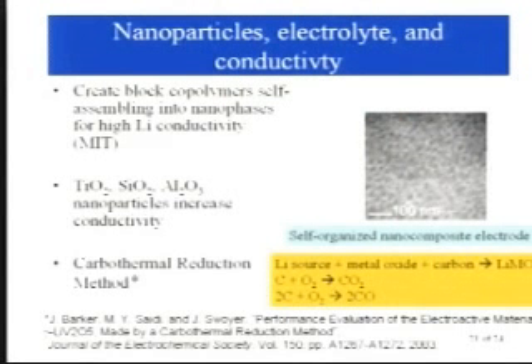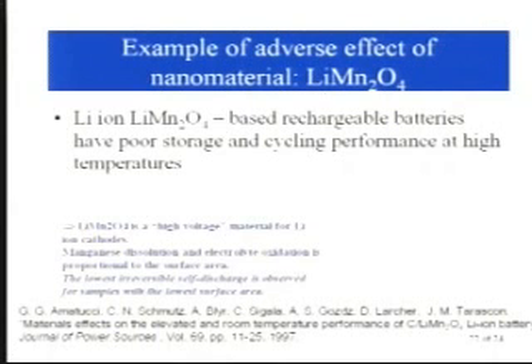And I mentioned the carbothermal reduction method a few times, and essentially what it is is use of grinding carbon in with a precursor, and there's a reaction of oxidation of the carbon. This is a very old metallurgical process, and this reduces the precursor and gives you a final product. And so there's a lot of interest in that. But lithium manganese oxide is an example of a nanomaterial, the downside to nanomaterials, because one thing that happens with high surface area is you increase the tendency of unwanted reactions, and that happens a lot with electrolytes and lithium manganese oxide.